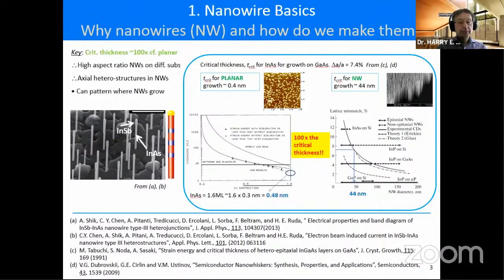And also this figure where I showed the indium antimonide, indium arsenide, shows that one can in fact modulate growth. So we can actually grow both inline heterostructures or longitudinal heterostructures as shown there, or we could do radial heterostructures, which we've used to control passivation or passivate surface states on the surface of these wires.